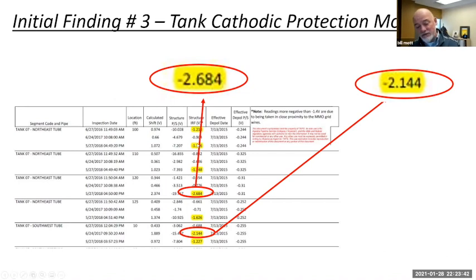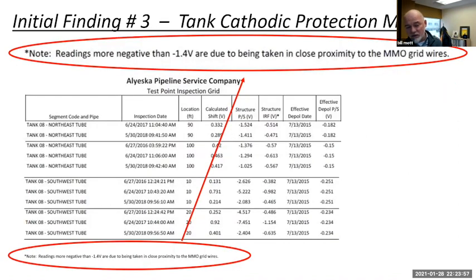And keep in mind that the IR-free data is what you subtract the depol data from to get the calculated shift. So if this data is bad, then the data you're using to compare against 100 millivolts is also in error. These are well beyond what Bob Gamow and NACE and we agree could be normal. Alyeska obviously realizes that there's some errors in their data, and they've caveated the data with this note that readings that are more negative than 1.4 volts are due to being taken in close proximity to the mixed metal oxide grid.